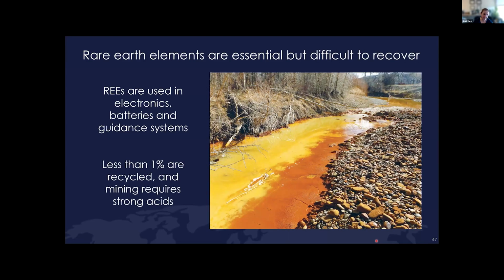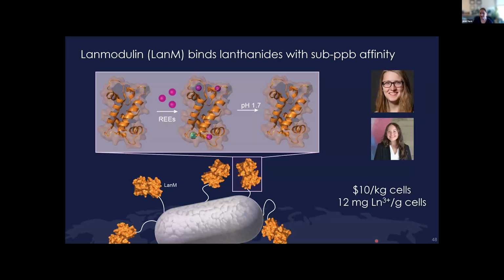The problem is we actually have enough of these metals in the US to use them right now, but less than 1% are recycled because of the harsh conditions required for leaching and regeneration of these systems. And so what we thought we could do was use a protein that had been known for about a decade called lanmodulin, and it's known to specifically bind to 3 rare earth elements. So we can see that here with these 3 balls.